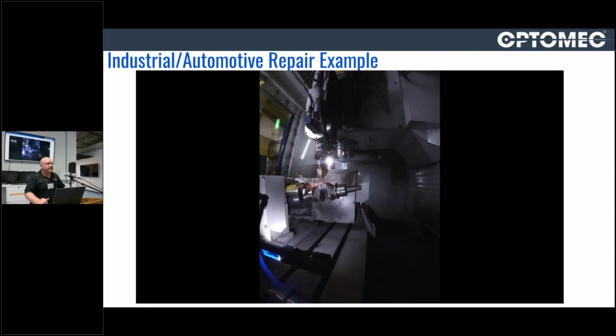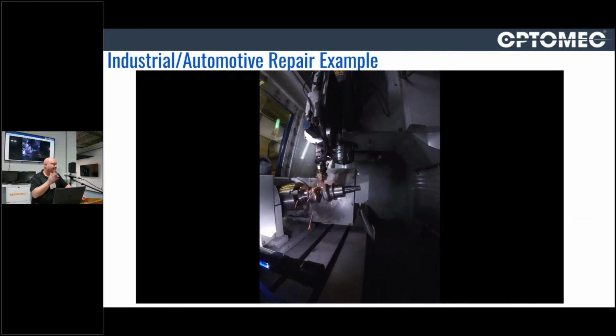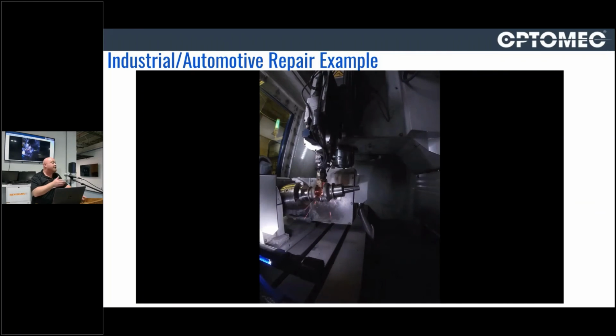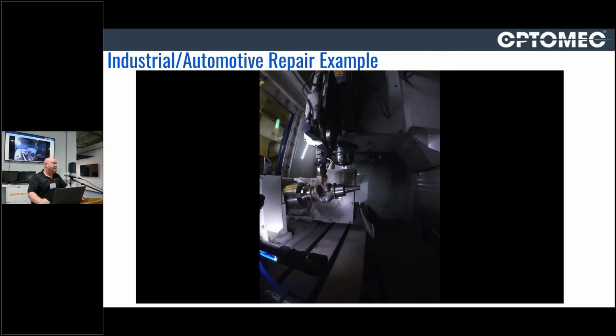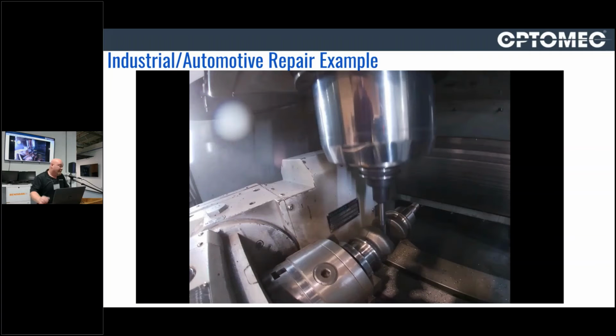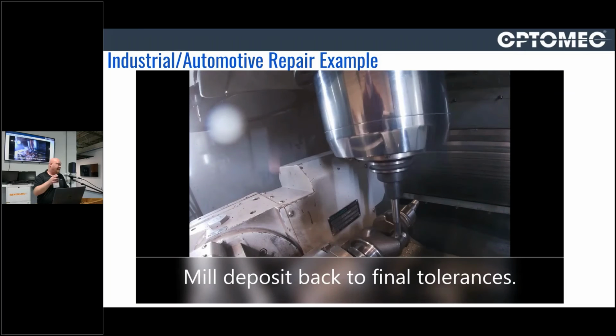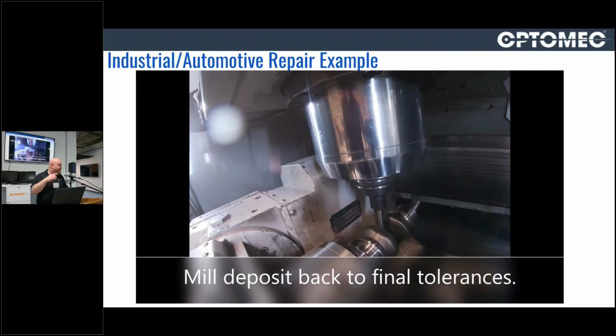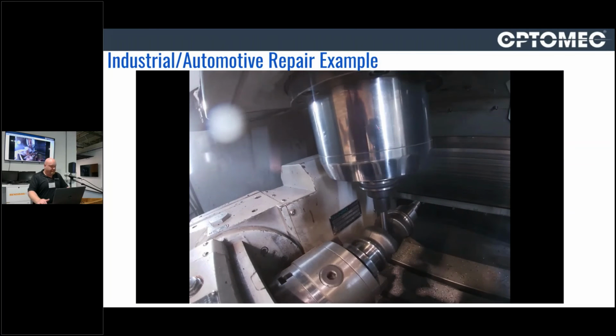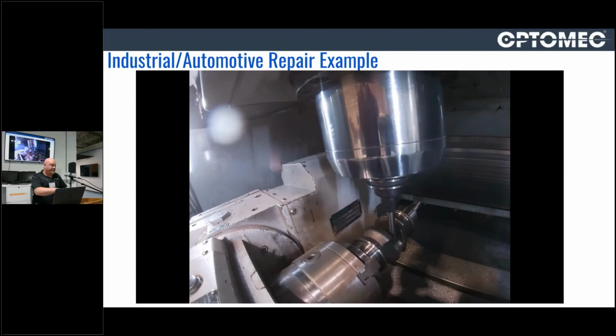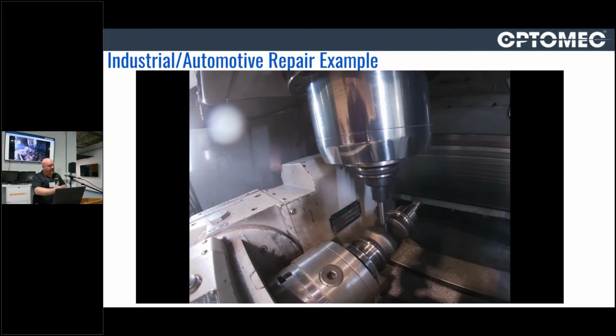The temper: if the material needs to be heat treated to get to wrought material properties, then it needs to be heat treated again. Really, it's very process dependent for us. I could have something that's a nice hot build and it'll be almost annealed. I could have something that cools very rapidly and it'd be very much stronger than your normal material. This particular one we did in the hybrid system, so we're able to go back and refinish that. You wouldn't refinish this part with a hybrid machine, but it's a cool demo.